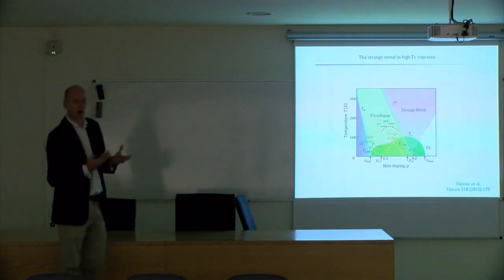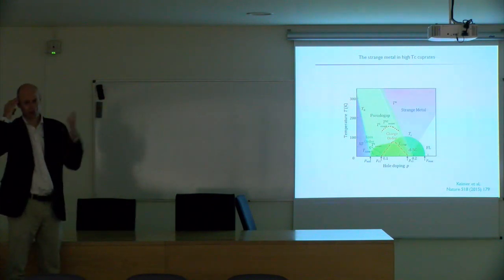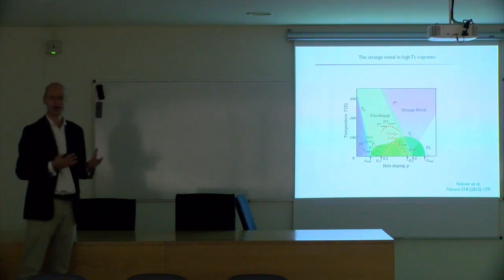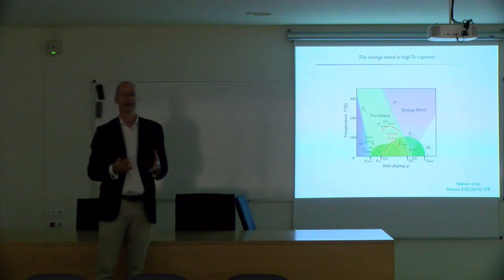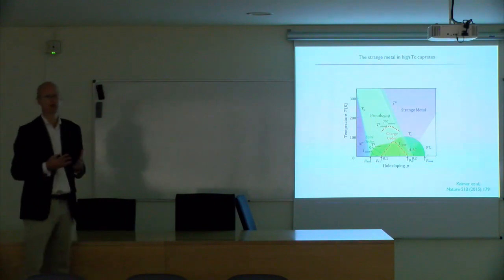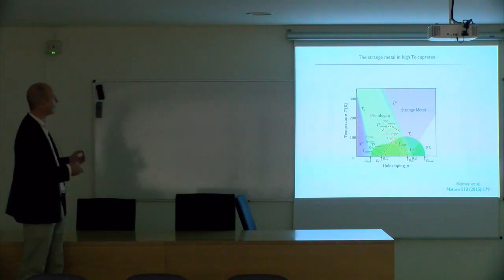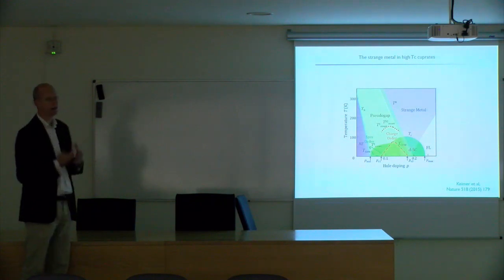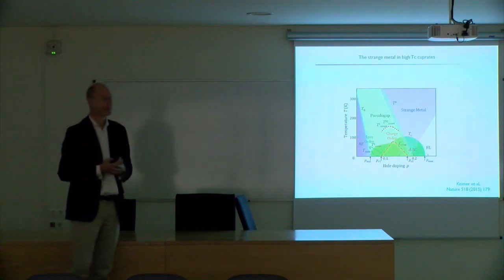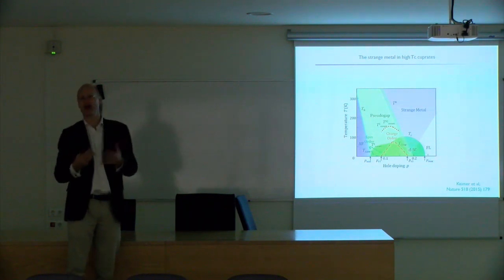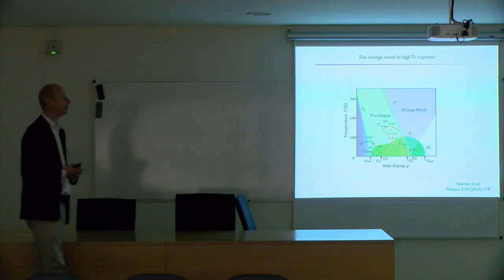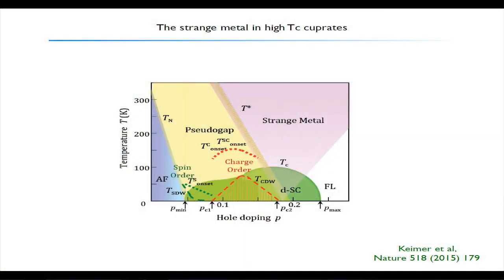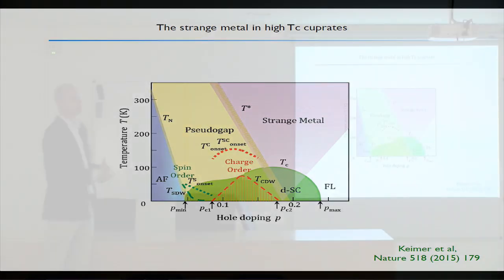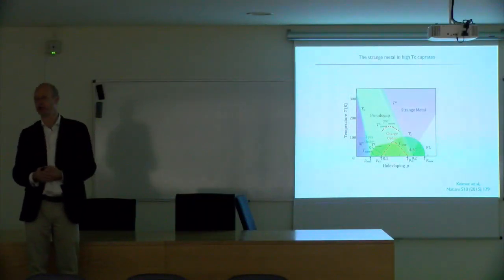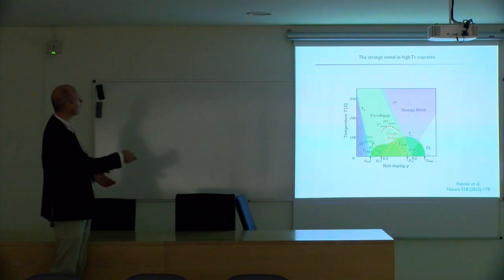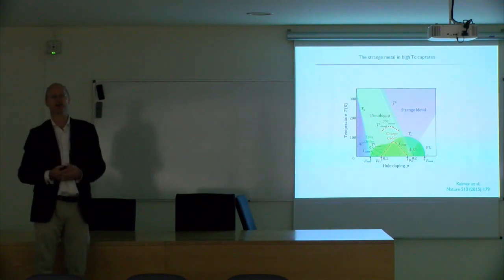Now this, we know from the standard theory of superconductivity, falls outside of its paradigm. In the usual way, the famous Bardeen-Cooper-Schrieffer theory of superconductivity, it is literally impossible to get superconducting temperatures, at ordinary circumstances, that are much more than 20, 30 Kelvin. So something here is going on that falls outside of the textbook condensed matter system. Now, actually, the superconducting region itself, below 100 K, does fall into this Bardeen-Cooper-Schrieffer class, but it's the onset, it's the regime above this temperature, that is where the mystery is.